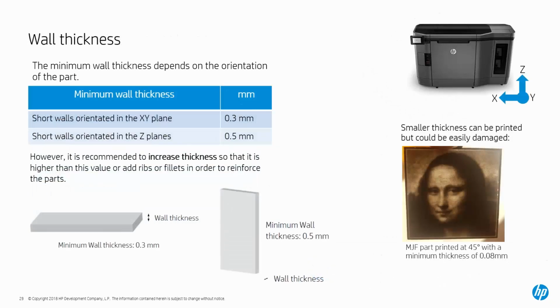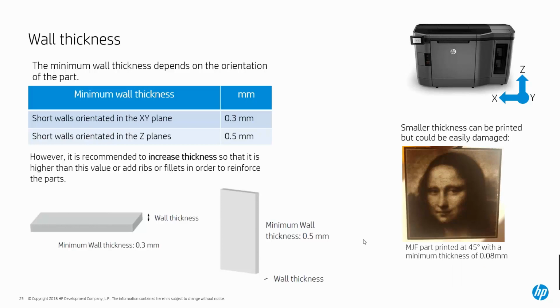Then you look at minimum wall thickness, depending on which plane you're printing the part in, whether it's oriented up in the Z or flat down in the XY. You can go down to 0.3 millimeter in the XY plane, or 1/2 millimeter in Z. So essentially, in my opinion, you just go back to the 1/2 millimeter rule. Minimum features are going to be about 1/2 millimeter, but there is a limit on wall thickness and how far it can overhang, because obviously if we made a 1/2 millimeter wall that overhangs too far out, it would be prone to warpage, right?